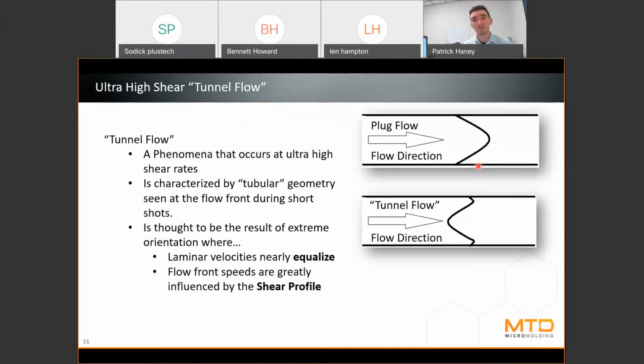However, when we get to ultra high shear rates, sometimes we experience a phenomenon that MTD has dubbed, instead of plug flow, as tunnel flow, right? And it is characterized by kind of a tubular geometry. So if we were to stop the flow down the middle of the flow channel all at once and then cut it in half, this is the shape that it would typically have, versus this is the shape that we end up seeing at ultra high shear rates. So we've characterized that as tunnel flow.